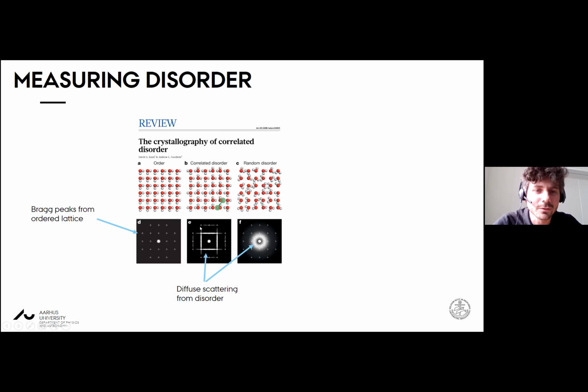And what you see is that, well, it's not so clear on this plot, but the Bragg scattering intensity is hardly affected by this type of correlated disorder. But in between the Bragg peaks, and this is on a log scale, you can see some diffuse scattering, and this is very sensitive. Okay, so this shows you that there is some strong correlation between neighboring hydrogen ions, atoms, in this crystalline form of water. And then obviously you can go to the completely disordered water over here where the correlations are lost. And now you see a very isotropic type of diffuse scattering. So we have lots of information available in the diffuse scattering, which is not present in the Bragg scattering.